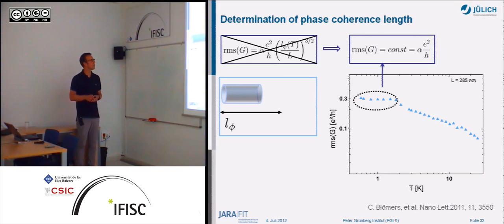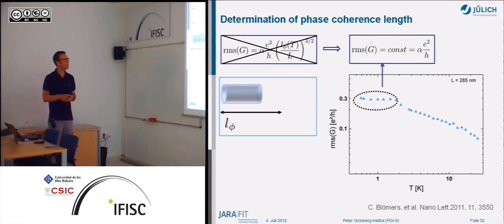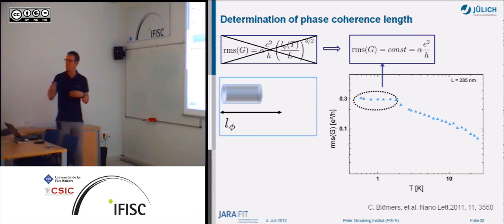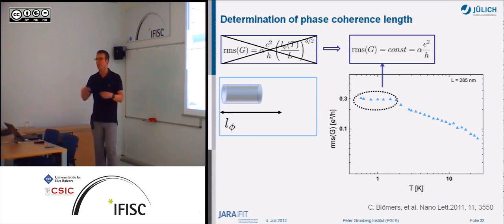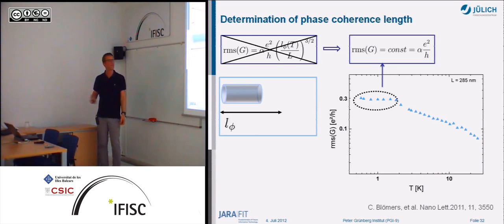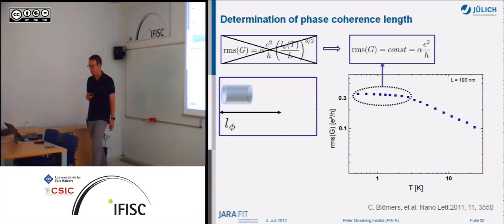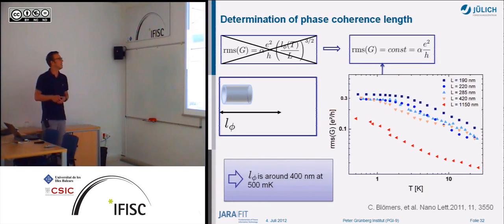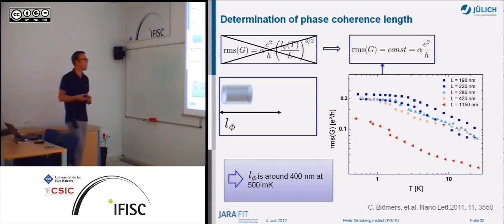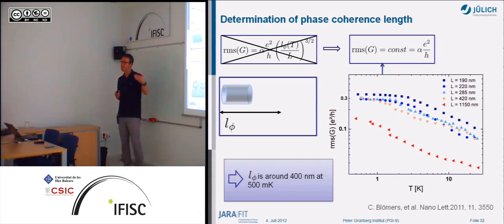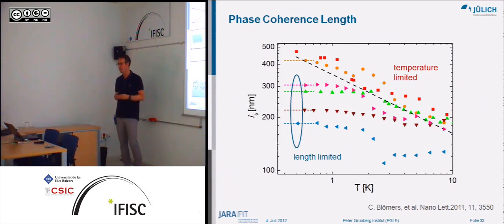But if you have now a very short one, then you see that at a certain temperature the phase coherence length gets longer than the nanowire, and then you see a plateau here in the RMS. Then you reach the point where the phase coherence length is longer than the nanowire, and if you decrease the temperature further, then you don't gain anything. Then you still remain with this constant root mean square here. It's the same for even shorter nanowires. So at the end, what you observe is that if the nanowire is shorter, then at a certain point you get a plateau, and the plateau means that the phase coherence length is now longer than the nanowire itself.